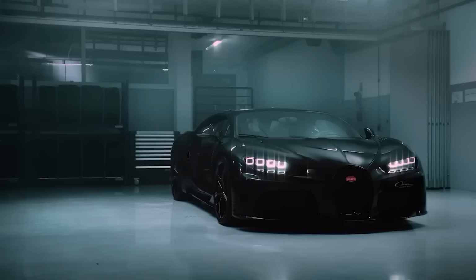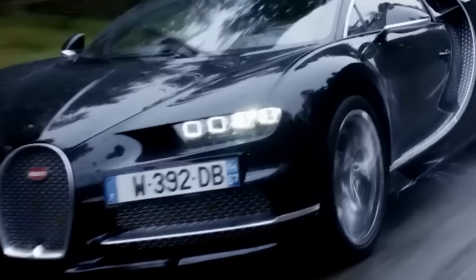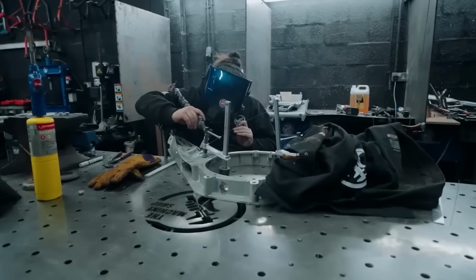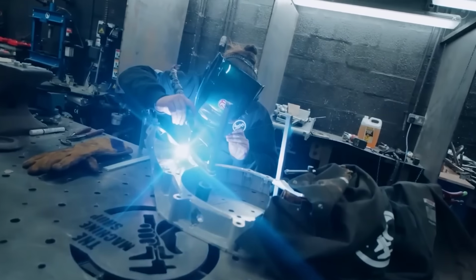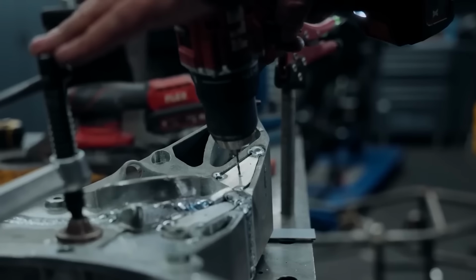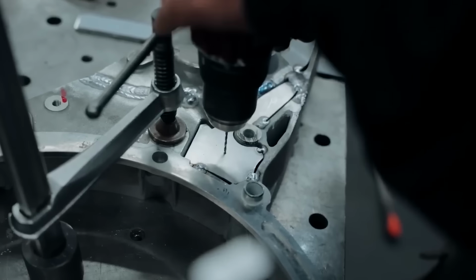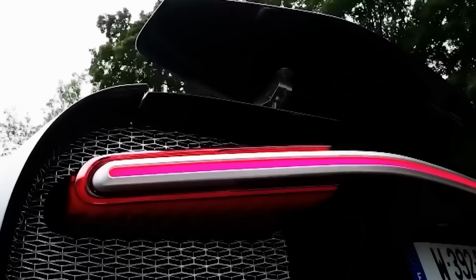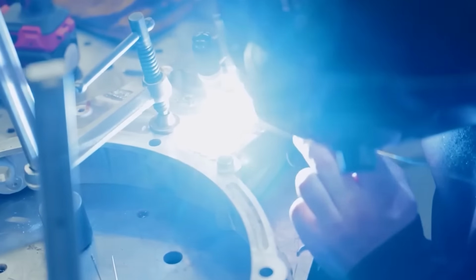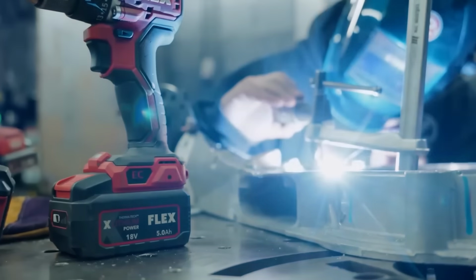Bob begins by preheating the entire component to around 200 degrees Celsius. This is non-negotiable with cast aluminum. Welding a cold casting creates violent thermal gradients, the metal expands unevenly, and the stress cracks what you're trying to fix. Preheating brings the whole part up to a stable temperature so the heat from the torch doesn't come as a shock. Once the mount is up to temperature and clamped securely to the welding table, Bob begins the main weld sequence.